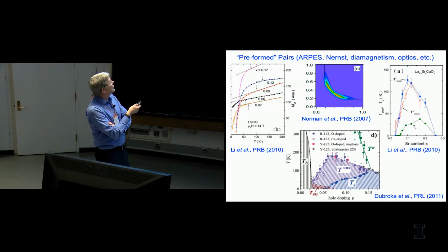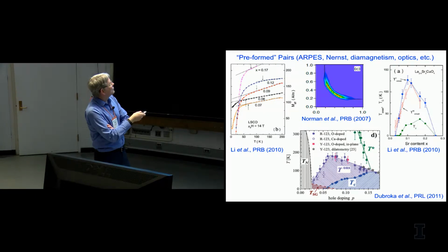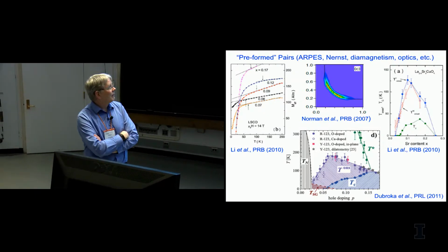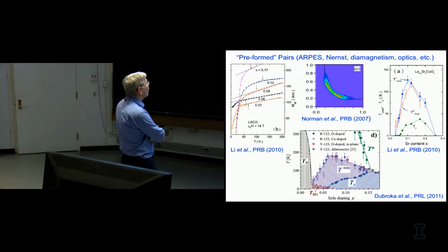And there's evidence for this. Photoemission data, of course, shows that large regions of the Brillouin zone are gapped out with an arc of excitations that typically shrink as you go down in temperature. But if you look at, say, optics data or Nernst data, there's also evidence that something that you could interpret in terms of preformed pairs cuts in at an onset temperature much higher than Tc. But of course, there are alternate interpretations of these data as well.